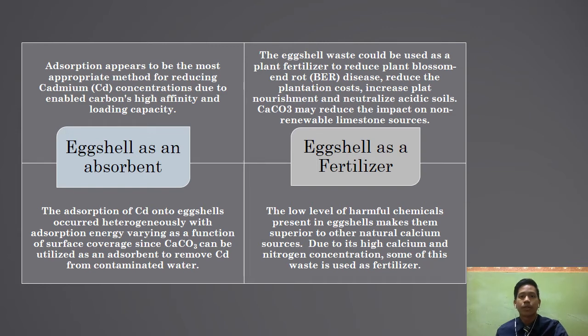For the next literature review, I would like to discuss about the eggshell as an absorbent. Adsorption appears to be the most appropriate method for reducing cadmium concentrations due to enable carbon's high affinity and loading capacity. The adsorption of cadmium onto eggshells occurred heterogeneously with adsorption energy varying as a function of the surface coverage, since calcium carbonate can be utilized as an adsorbent to remove cadmium from contaminated water.